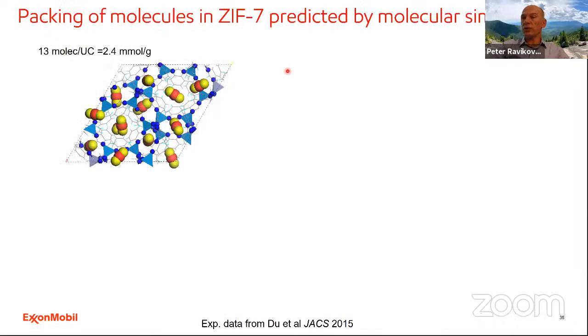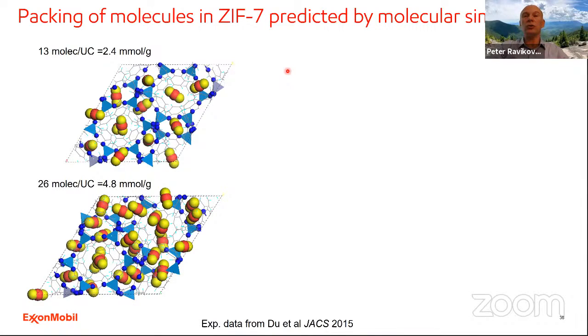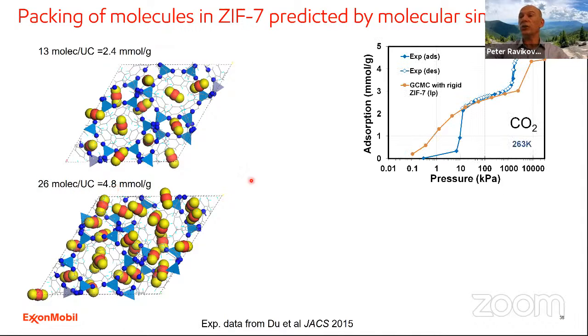You can also do molecular simulations of individual isotherms with rigid structures, and look at molecular configurations at different loadings. And it turns out that if you take the ZIF-7 large pore structure, you can simulate adsorption corresponding to almost double the experimental capacity. So in other words, you can simulate adsorption corresponding to this first plateau. And then you can simulate adsorption corresponding to this second plateau. Which is telling you that whatever transition occurs in this second step does not change the structure dramatically. It's a rather subtle, small rearrangement within the structure.